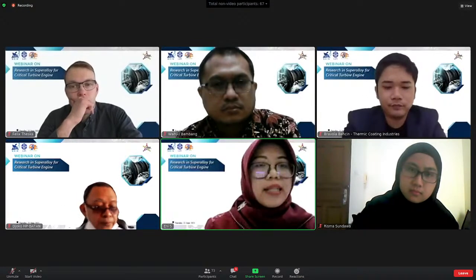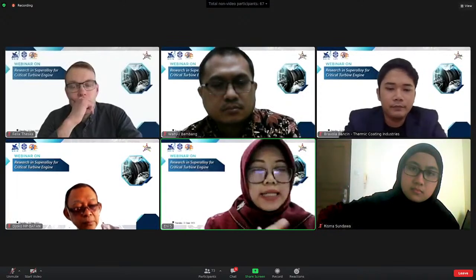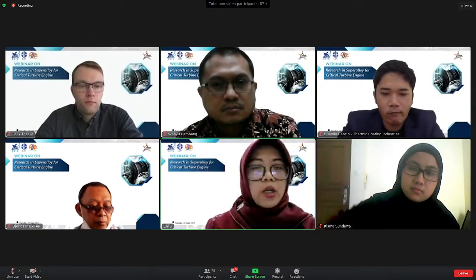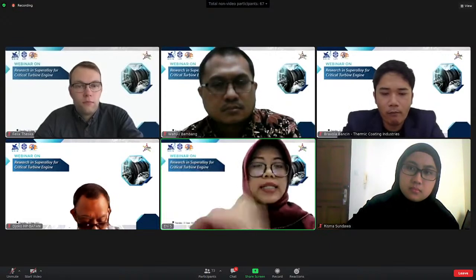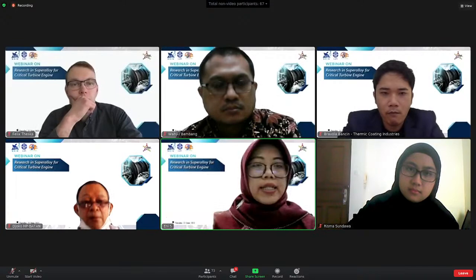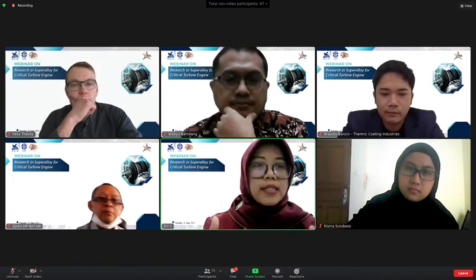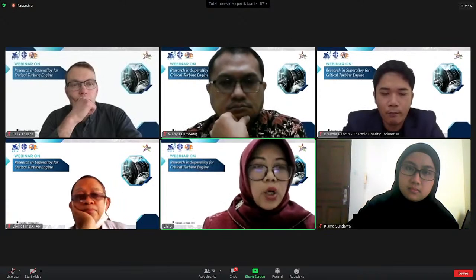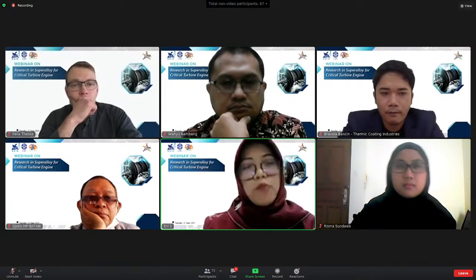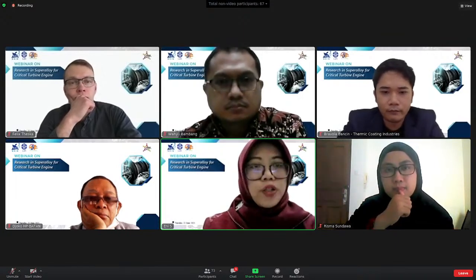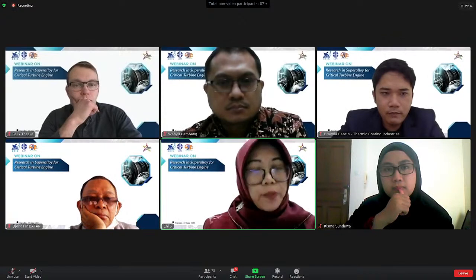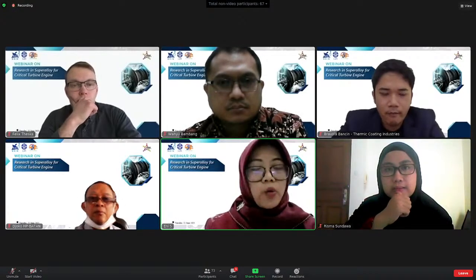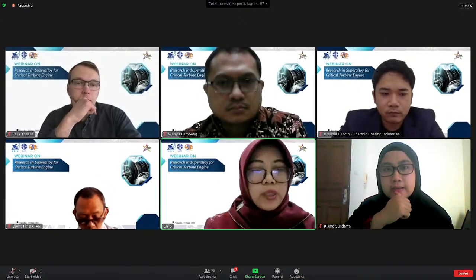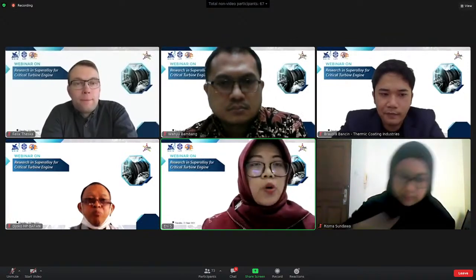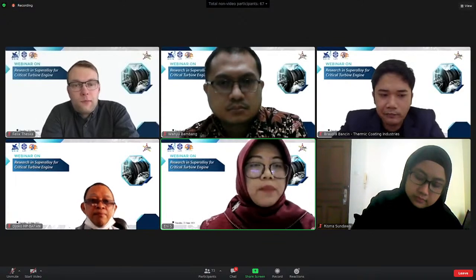aluminum could be identified. In this case, because we evaluate our coating system from the surface, there is a limitation in using XRD analysis. Therefore, in all the XRD results, we cannot identify the beta nickel aluminum in our samples. But I have experience using TEM to evaluate each layer, though I didn't show it here. It means that in the coated sample, after heat treatment, beta nickel aluminum can be formed in the bond coat layer.